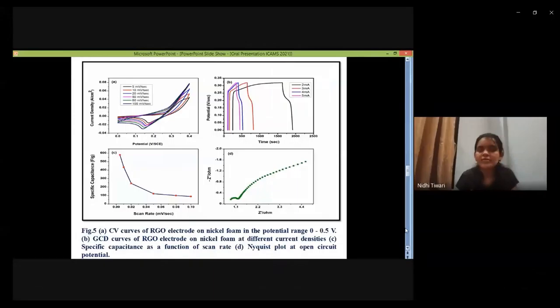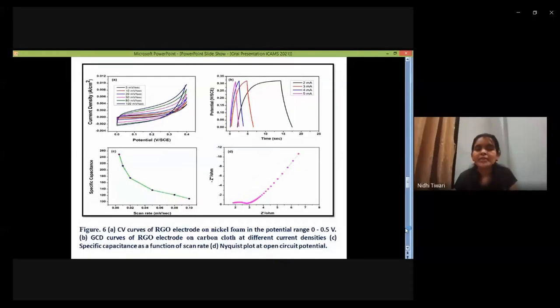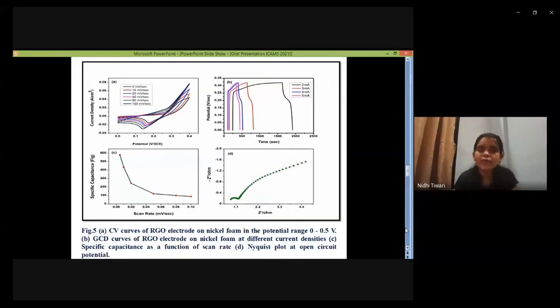These are the supercapacitive studies: CV, GCD, specific capacitance comparison, and EIS plot for RGO on nickel foam. Then these are the supercapacitive property studies for RGO on carbon cloth. So you can see the area under the curve for RGO on nickel foam is greater, so the capacitance obtained is greater.